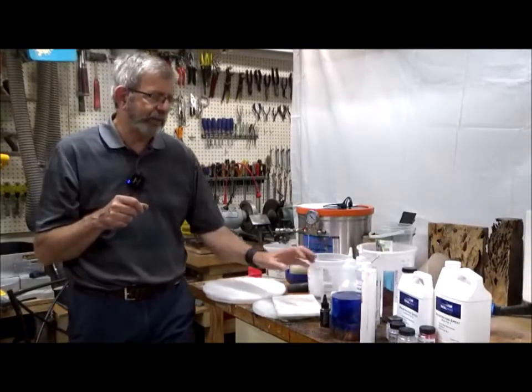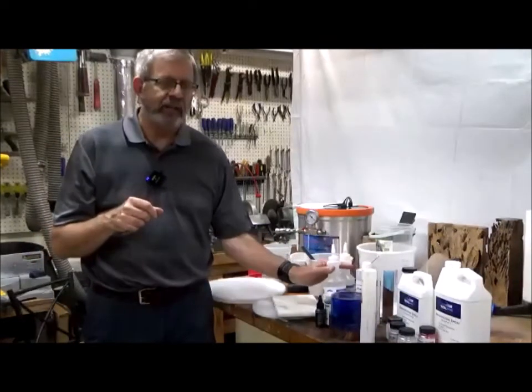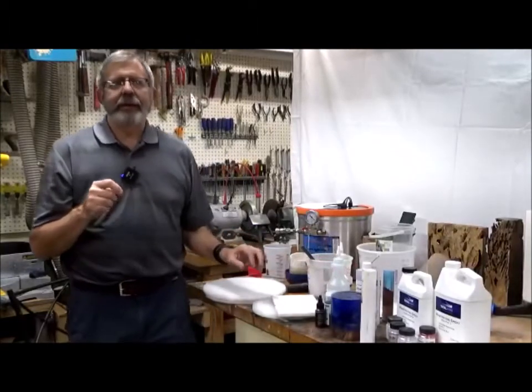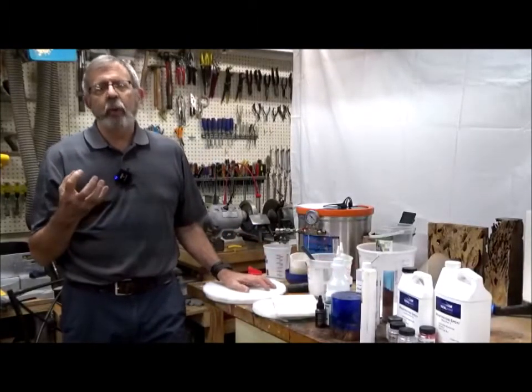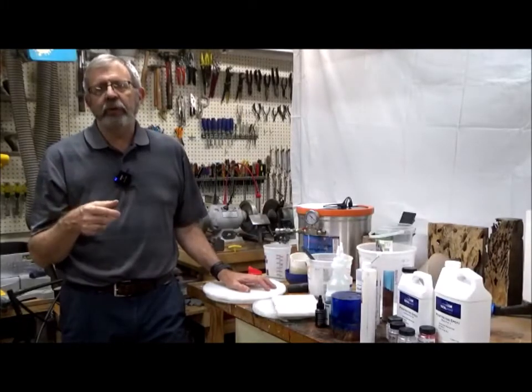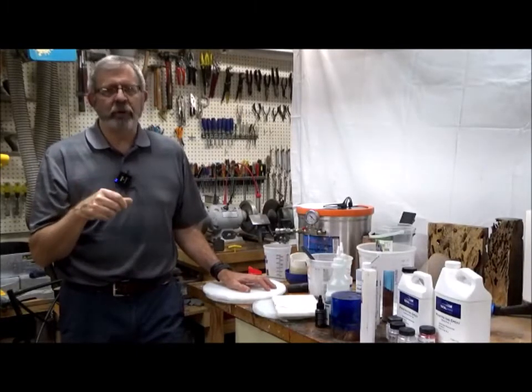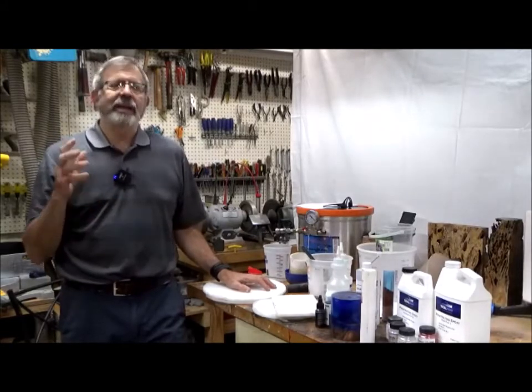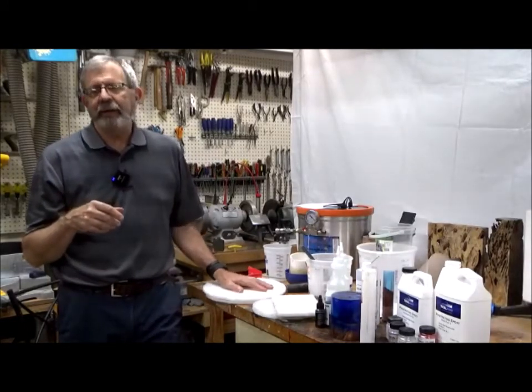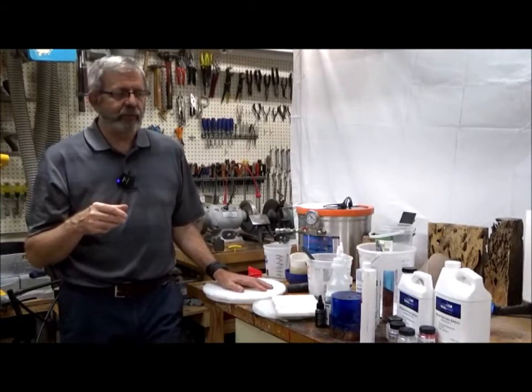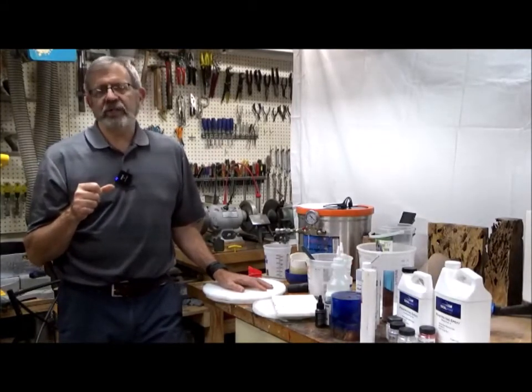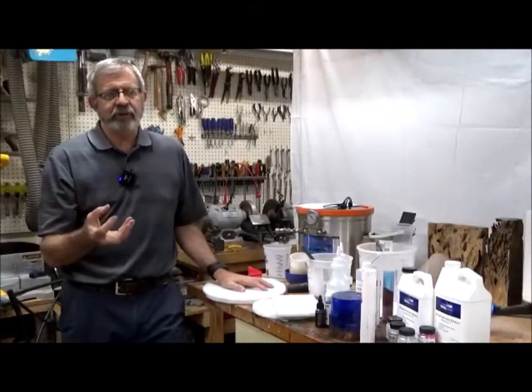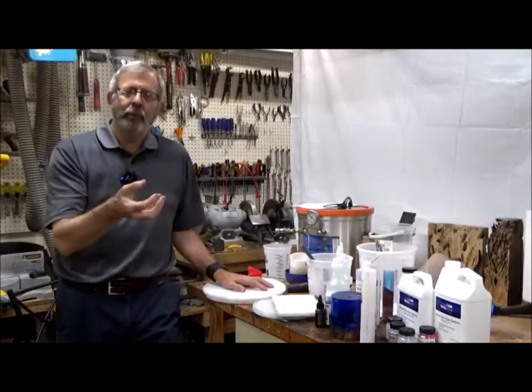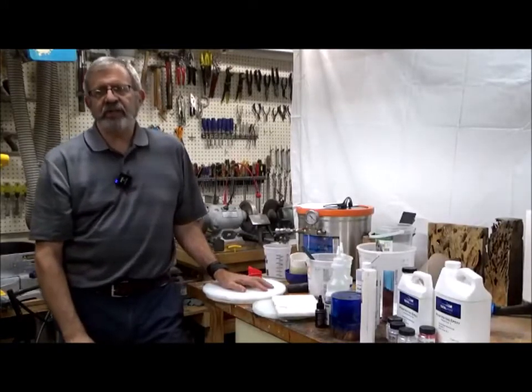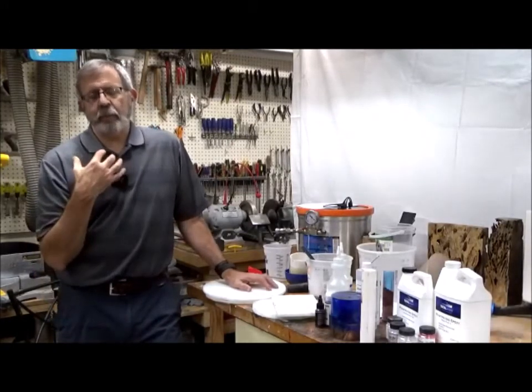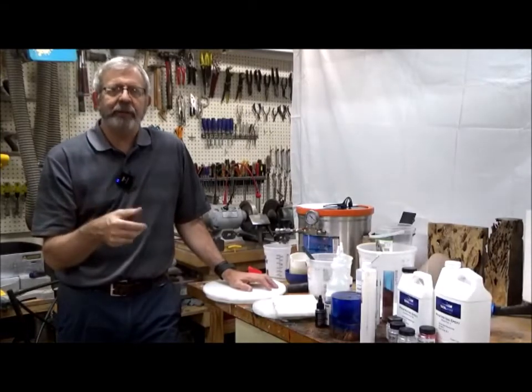Particularly with the polyurethane resins, not so much with epoxy, if you have any moisture at all, you'll get a white foam on the surface of what you're doing. It takes just a little bit of moisture. If you do it on a humid day, it can happen. So it's very important that everything be very dry. That's one of the downfalls. Epoxy is not as critical, but you still get some problems: if there's moisture in it and you get heat, the moisture gets drawn up through the wood. So that's one of the reasons I stabilize everything that I'm casting resins against.